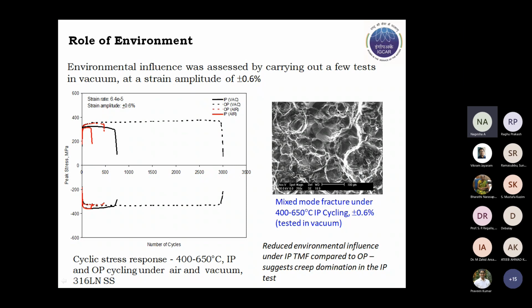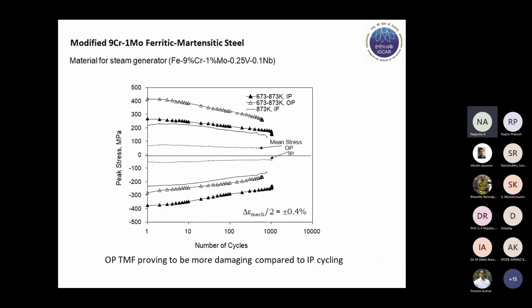And in fractography also, we saw extensive signature of creep damage, which manifested in the form of mixed mode fracture under 400 to 650 IP-TMF.